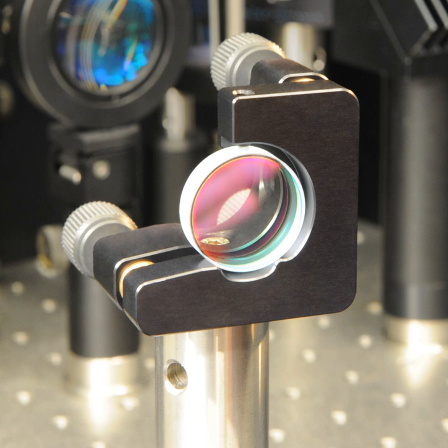The reflections from the low-index layers have exactly half a wavelength in path length difference, but there is a 180-degree difference in phase shift at a low-to-high index boundary, compared to a high-to-low index boundary, which means that these reflections are also in phase.